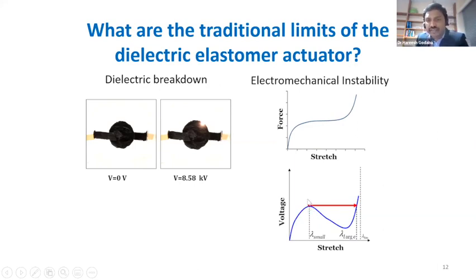And once the voltage is further increased, you'll see that there is no stable state close to the stretch. So the membrane tries to jump to this very large stretch state. And during that process, the membrane also thins, because the elastomer is incompressible. But as the membrane thins, it is possible that it will encounter dielectric breakdown before it reaches the next stable state. So the largest observable stretch will be this lambda small that is pointed by this N-shaped curve. And this comes to about just 30% linear strain, which generally was the traditional limit of this type of dielectric elastomer actuators. So generally, once we get this 30% strain, there is breakdown, and then the membrane obviously cannot stretch any further.